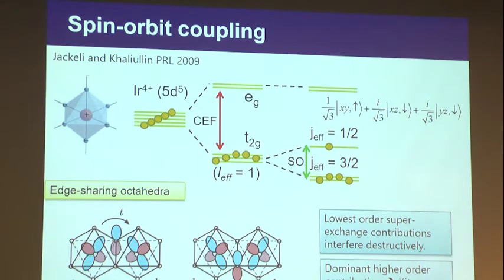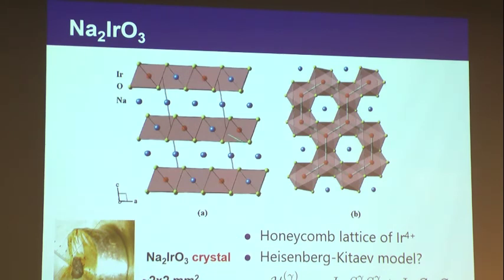Okay, so that's great. They provided the direction: if you take a strong spin-orbit coupled material which has these edge-sharing octahedral magnetic pathways, then you might be able to realize Kitaev's quantum spin liquid. Immediately following that prediction, there was a material, sodium iridium oxide, which was synthesized by many groups, but Yogesh Singh and Philipp Gegenwart published first, and they were able to grow a fairly large single crystal of sodium iridium oxide. You can see that the structure is exactly what you expected. First of all, it's a honeycomb lattice, formed by octahedra of iridium and oxygen, connected through an edge-sharing network. So this is almost exactly what you expected from the Khaliullin and Jackeli proposal.